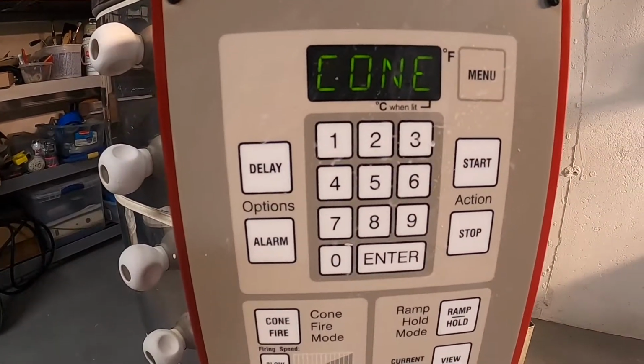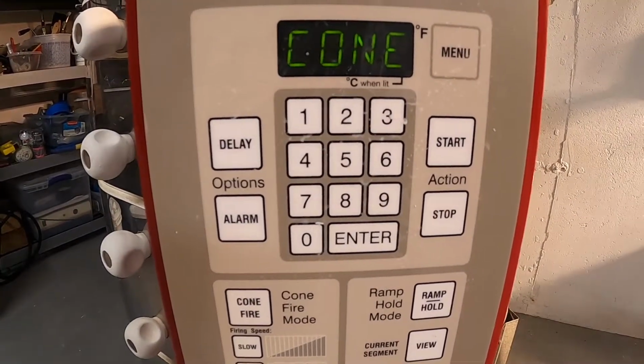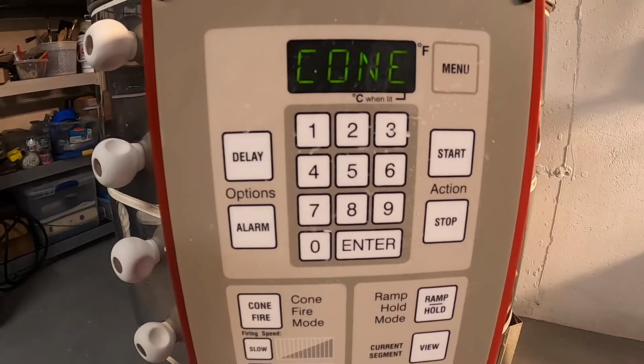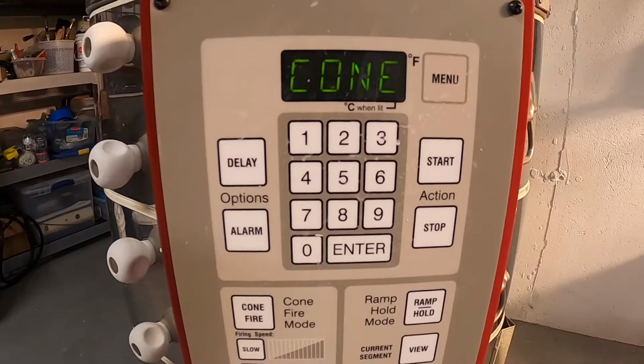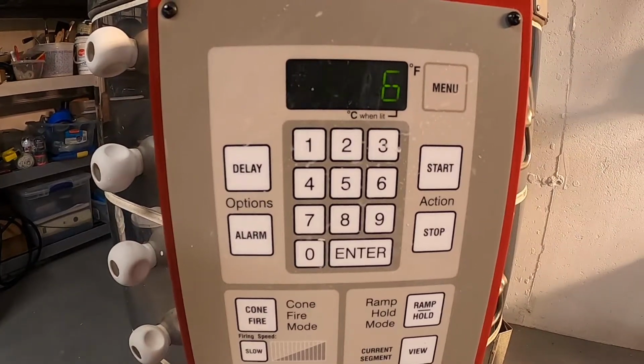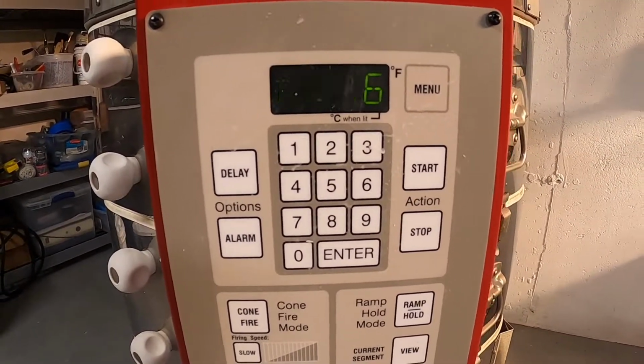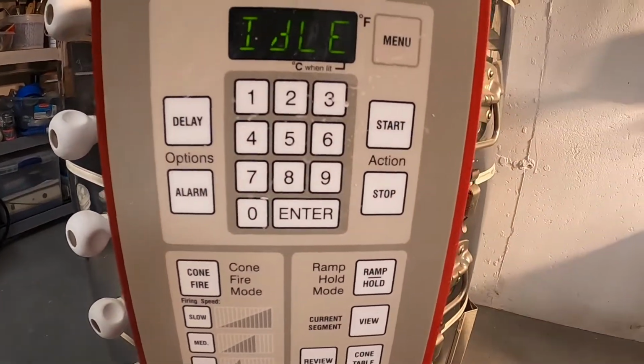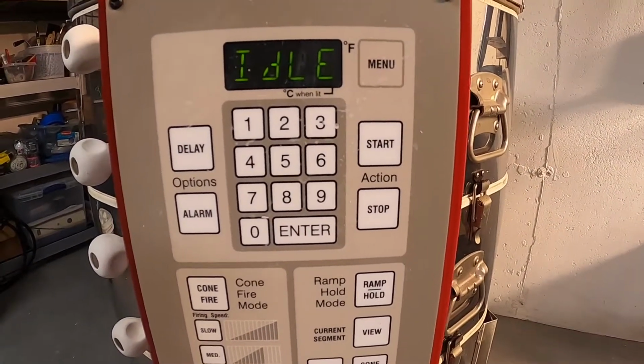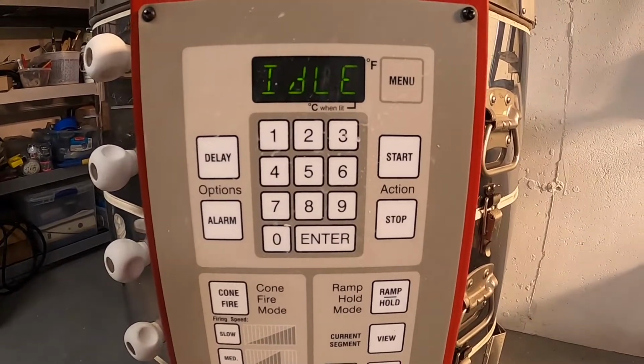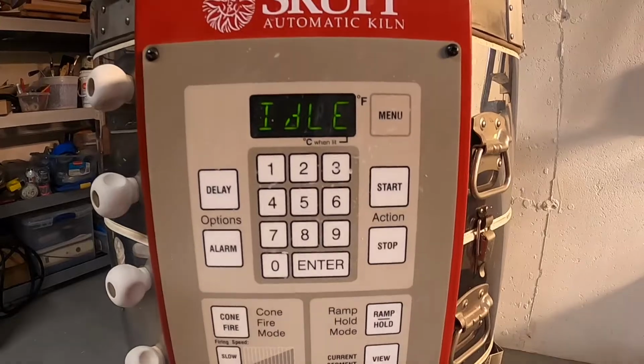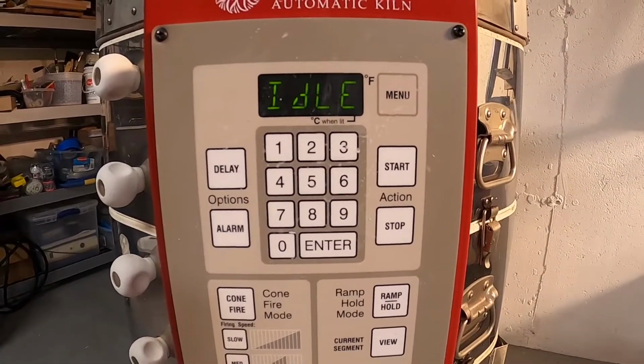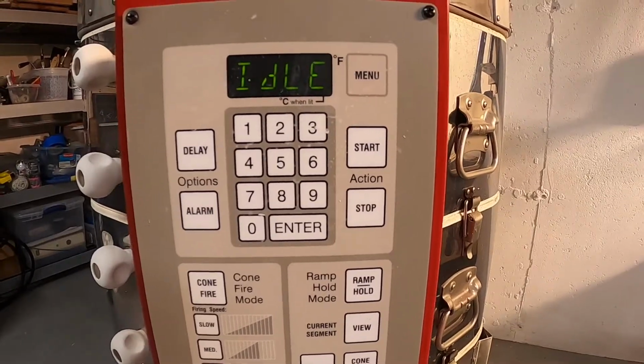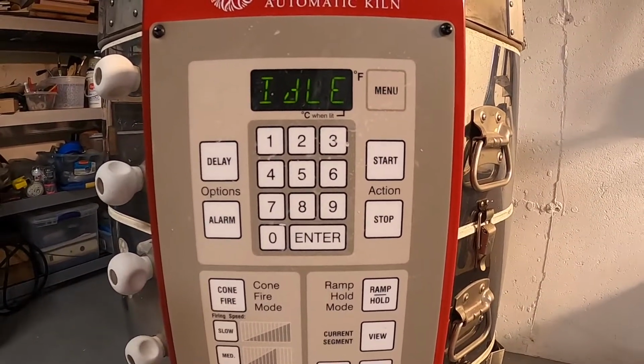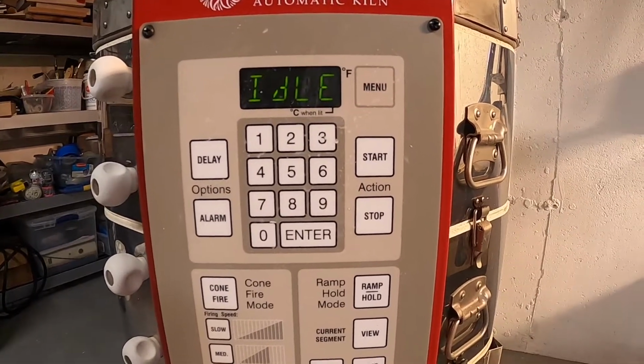So, enter. What this means is that this kiln, when it's on, is not going above 200 degrees Fahrenheit for 2 hours. That way all the moisture that's left in the clay has time to evaporate. In other words, no steam will be trapped in my clay and then explode. You can still have explosions if your clay is too thick. Air bubbles don't necessarily cause the explosions. It's the moisture that's trapped in the air bubbles that causes the explosions. So again, to prevent explosions in your kiln, preheat your kiln for a couple hours, so all the moisture left in your clay can evaporate and the steam can go out.